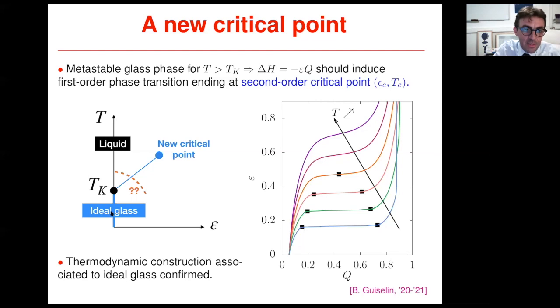And the theory predicts this transition between the liquid and the glass at the Kauzmann transition. So now we have a whole new plane to explore in the presence of this epsilon field. And what theory predicts is that out of this metastable glass phase here will emerge a line of first order transition here at finite epsilon, ending at a new critical point here at a finite temperature and finite value of the field. So this blue line here is the direct consequence of the metastable nature of the glass just above the Kauzmann transition here in the theory.